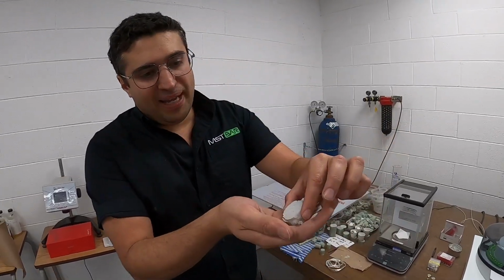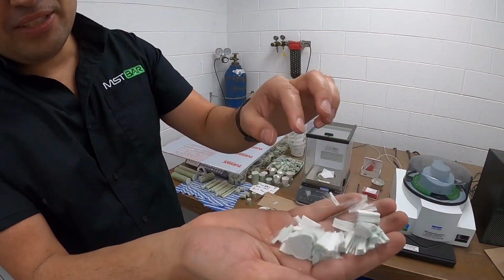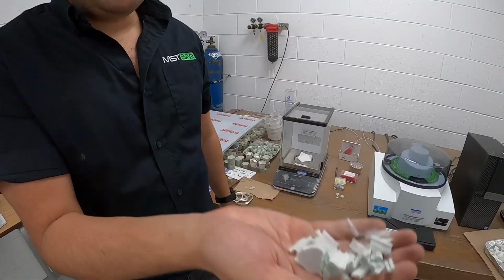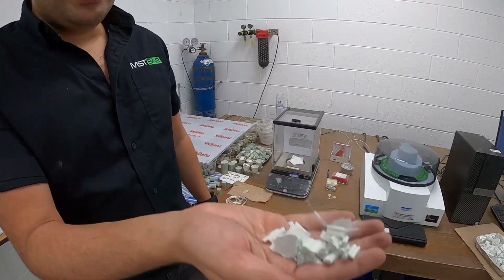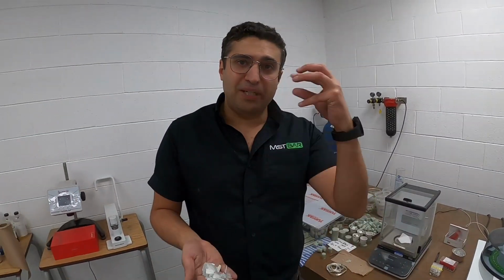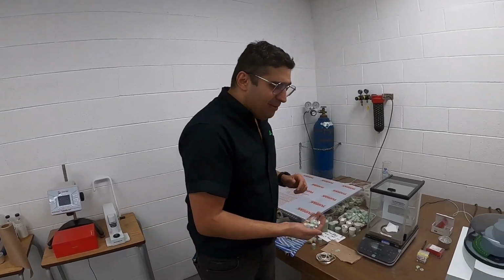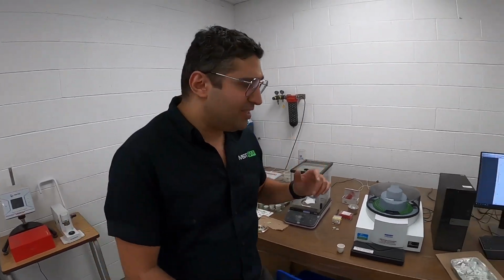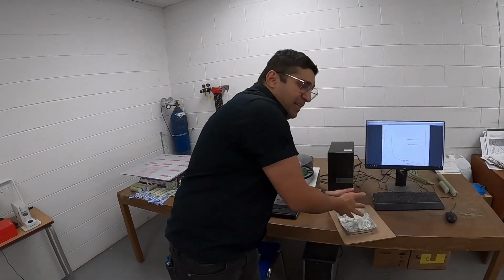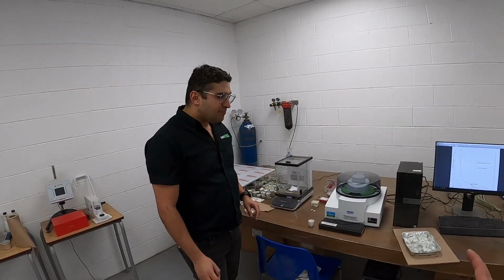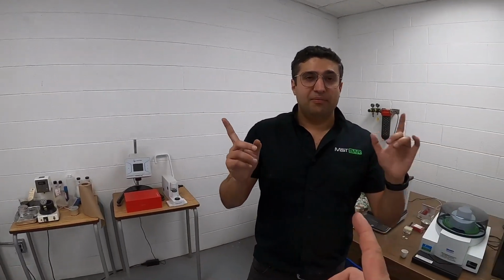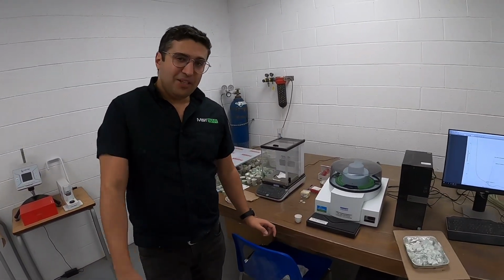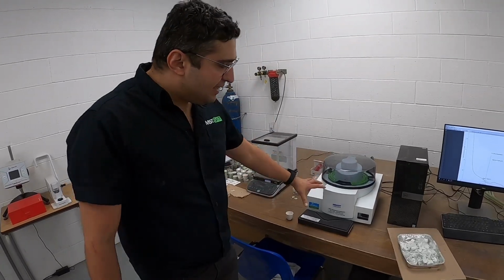And what's left, Matt, is a piece of fiberglass rebar. That's what you see in my hand. We weigh this and compare its weight to the overall, and that's how we say about 80 to 85% of this material is glass. So the temperature that you set it at, is that to break down the polymer? The polymer only, and remove moisture. So you're not weighing water? Exactly.